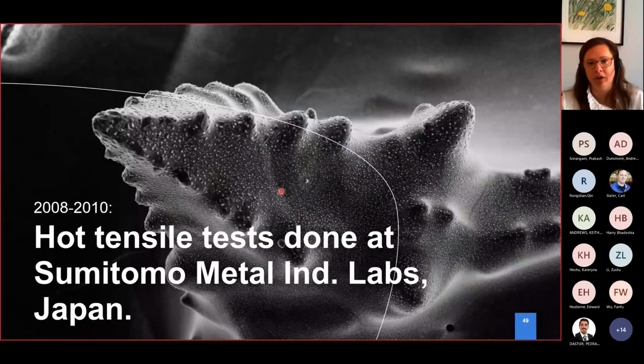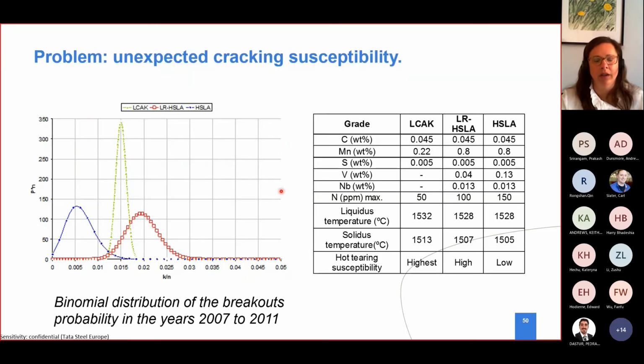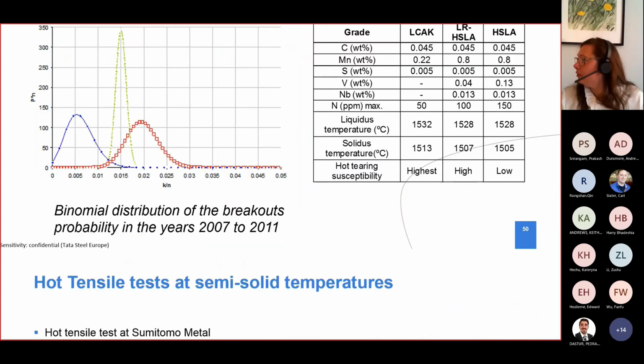Some examples of a hot tensile test. By the way, this is a steel dendrite of one of our steels. A long time ago, we did some tests in Japan together with Sumitomo, a hot tensile test with their in-house machine. What was our problem? We had one of our steels that had way more cracking susceptibility than two other comparable steels. It was a very simple steel. It had really nothing in it. You can look at the composition here compared to the other two.